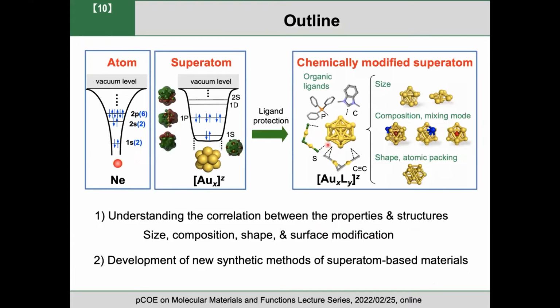So chemically modified or ligand-protected clusters can be viewed as superatoms, chemically modified superatoms. And the unique feature of chemically modified superatoms is that they have a variety of structure parameters, like the size of the core and the chemical composition of the core. We can also change the shape of the metallic core, and we can also choose the chemical species on the surface.